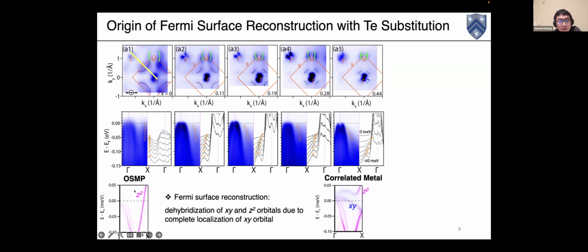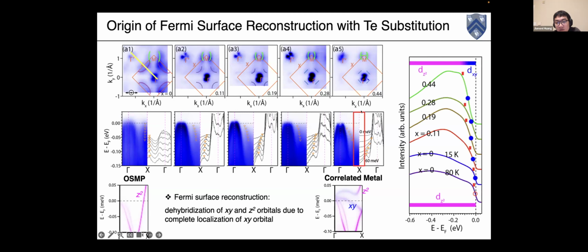And then we compare with calculations done by Dongyu and Qimiao, and actually in the OSMP phase, they find that there's a dz square orbital that crosses the Fermi level around this X point, and that corresponds to the nearly vertical band we find. This dz square in the correlated metal phase is cut by the XY orbitals and shows a large hybridization gap at the X point. So this tells us that this Fermi surface reconstruction is caused by the dehybridization of the XY and dz square orbitals due to the complete localization of the XY orbital. And we can track the hybridization gap of the XY band and the dz square band and find the hybridization gap actually closes at the iron tellurium end.